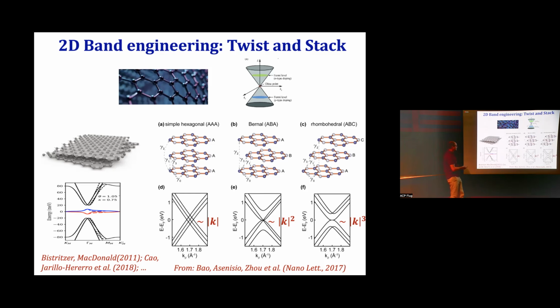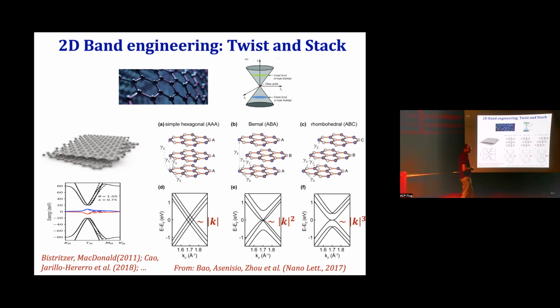And electronically, it turns out that the natural one is not the most interesting one. As you might guess, for 3 layers of graphene, the most interesting one is the rhombohedral one that has the flattest dispersion close to zero energy. Graphite is just continuing to stack it this way. The electrons move mostly along the layers. So you see these, right.